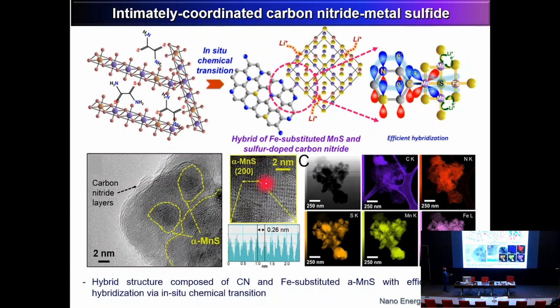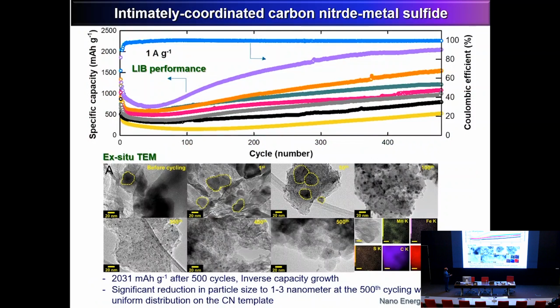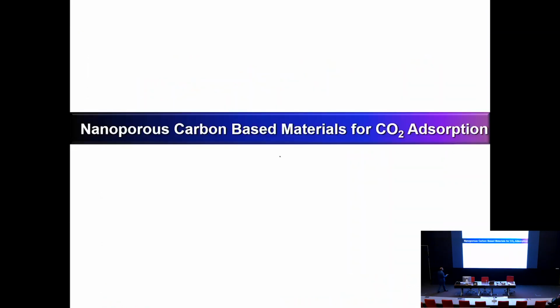So in this case, we use the manganese sulfide integrated with the carbon nitride and then introduce the iron into the manganese sulfide. So we get the iron-substituted manganese sulfide nanosheets in the carbon nitride material. Interestingly, when they increase the number of the cycles, the performance increases. The nanosheets are converted into small nanoparticles, and that improves the charge transfer. So the performance is almost 2031 milliampere-hour per gram.